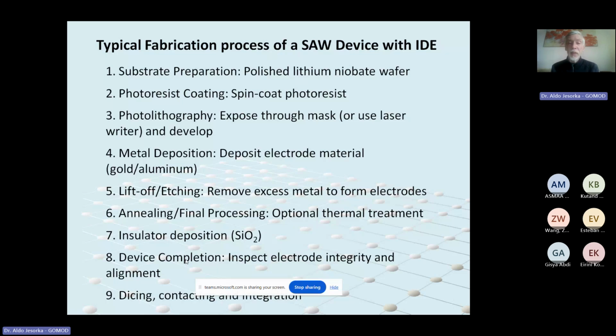Then comes a lift-off or etching. You remove the excess metal to form the electrodes, and it's not just the electrodes; the contact pads are also typically connected to this. You then do an annealing and final processing step, an optional thermal treatment, and if you want to use a liquid environment around the sensors, you put an insulating layer on top of the IDE, so they are not short-circuited in the medium.